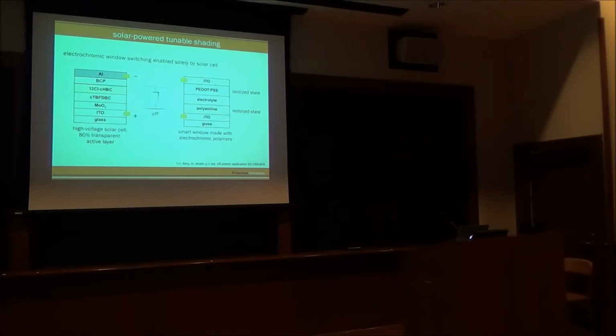That's the idea. So this is our solar cell stack. We've got our electrodes, we've got our donor and acceptor layer, and then there are some interfacial layers in there. This is our electrochromic window. You saw the characteristics of polyaniline. We can change the color of polyaniline through a redox mechanism. What that means is we're shuttling electrons back and forth. So you need an electrolyte that helps you shuttle electrons back and forth.